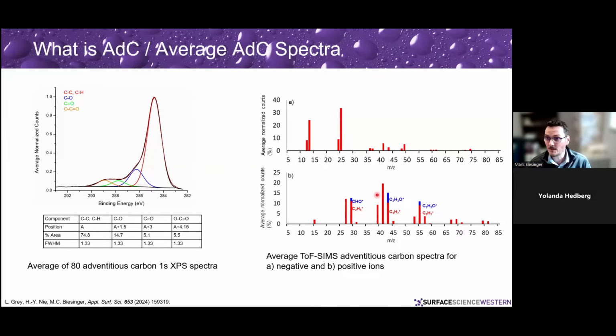If we look at TOF-SIMS, which is another technique that can look at this adventitious carbon, we actually use adventitious carbon fragments to calibrate our TOF-SIMS spectra. You can see we've got just a small fragmentation pattern, not a lot of very large fragments. It dries off very quickly. We have some oxygen components as well in the positive ion spectra. And so, again, this reiterates the thought that these are short chain volatile organic components that are sitting and sticking onto these surfaces.